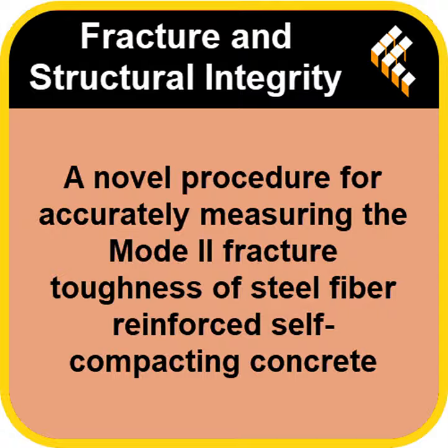But the really clever part, as you mentioned, wasn't just comparing old TTC to new MC. They used 4 different types of specimens to really isolate what was going on. Exactly. Good experimental design. First, the baseline, plain SCC, no fibers at all, just the basic concrete strength. Makes sense. Then the old flawed standard. That was Series 2, TTC. Through thickness crack. Fibers are mixed throughout the concrete block, but because the crack is saw-cut, absolutely 0 fibers cross that initial crack plane. This gives you that unrealistically low toughness value.